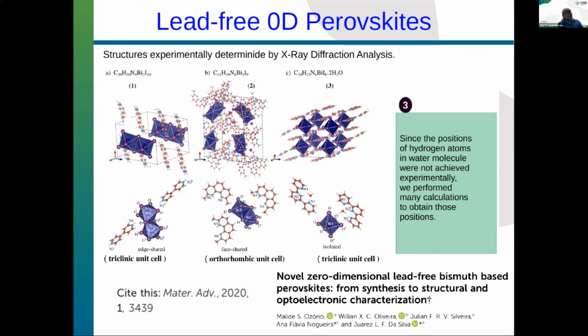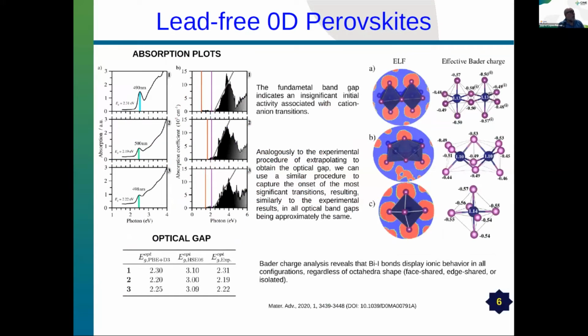We calculated all these structures. We helped to improve the understanding of one of these structures concerning the position of the hydrogens, because we performed several calculations to improve the XRD, the X-ray diffraction, interpretation. We arrived at a conclusion about what should be the best structure. And from that, once we extracted the refinement, we studied the optoelectronic properties. Of course, I summarize the most important results here. The published paper contains a lot more results than those shown here.